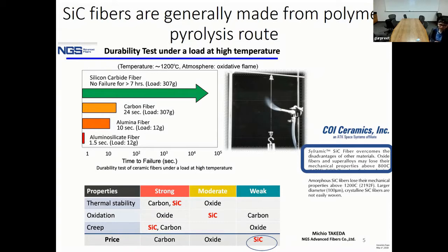Carbon fibers are selling at $140 per kilogram compared to silicon carbide fiber, which is 18,000 euros per kilogram. And it's because the market is small compared to carbon fibers. And then the silicon carbide fibers are prepared at 2000 degrees Celsius. So higher temperature, more energy, increased costs. And I would also like to mention that there are 4 companies that are able to manufacture high aspect ratio silicon carbide fibers, and 3 of those are based in Japan.